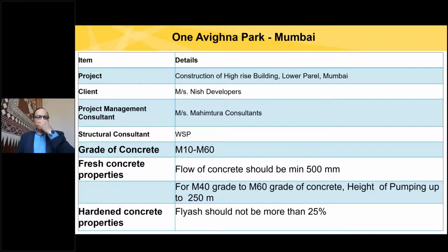This project is called the One Avighna Park project, again in Mumbai. And the grade of concrete varied from M10 to M60. Now look at the condition, fresh concrete and hardened concrete. For the fresh concrete, the flow should be 500 millimeters. And look at the height of pumping. The height of pumping should be 250 meters high. Please remember, 250 meters is 1/4 of a kilometer. Pumping water to 250 meters itself is a very challenging thing. Therefore, pumping concrete to 250 meters is really challenging. And fly ash should not be more than 25%. That was the requirement for the project.